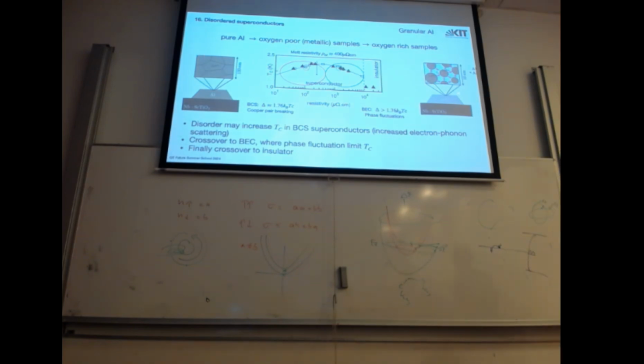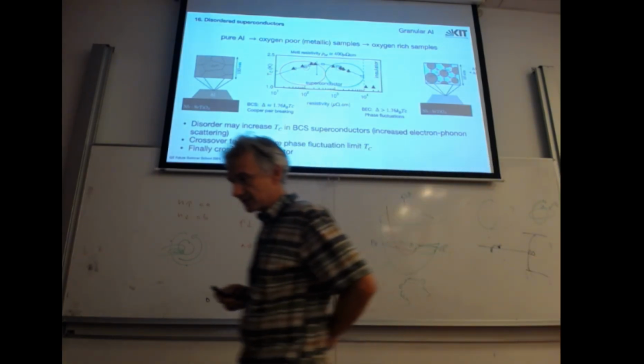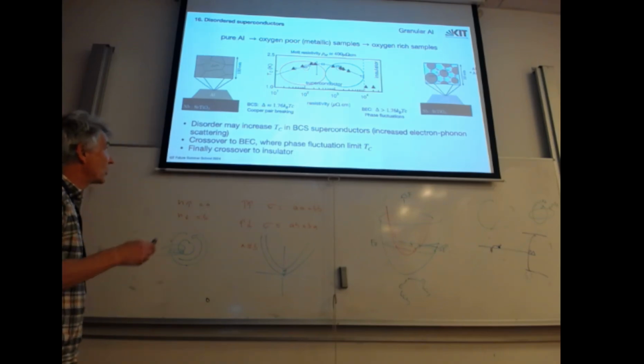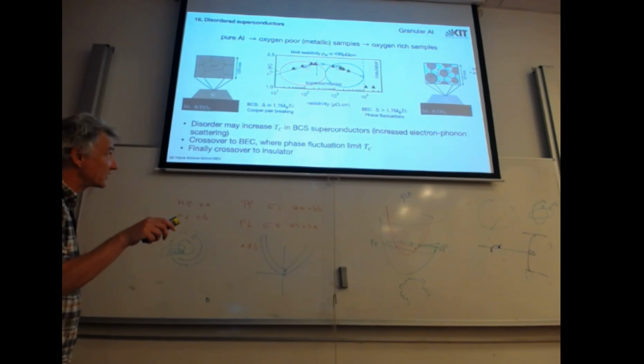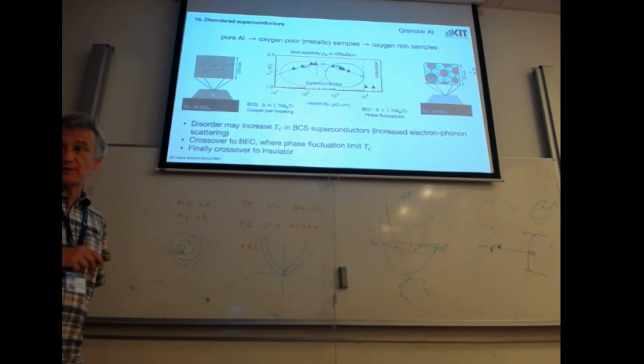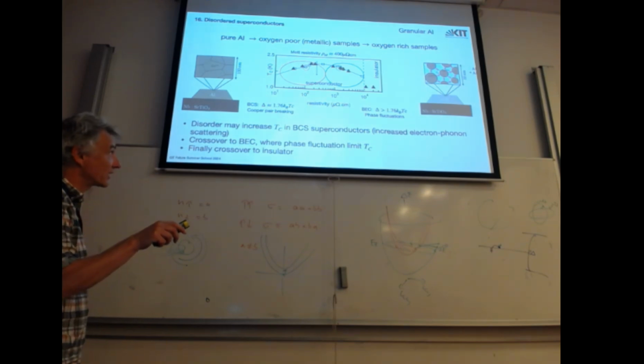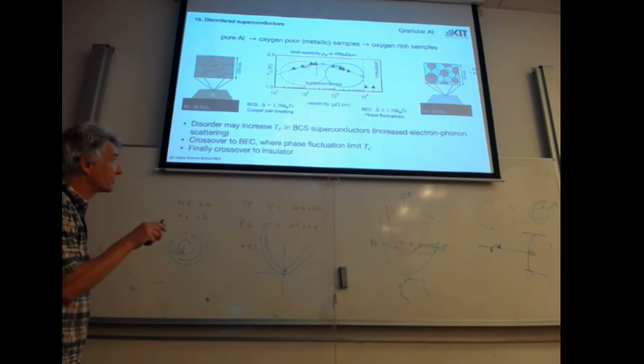And if you increase oxygen, you have aluminum grains which are separated by aluminum oxide. So we start to have grains here already, because it grows crystalline, and then the grain boundaries will be filled with oxygen, and you will decouple those grains. The degree of oxidation can be seen by the normal resistivity of the film. The more oxide, the more tunnel junctions you have, and the higher the sheet resistance.